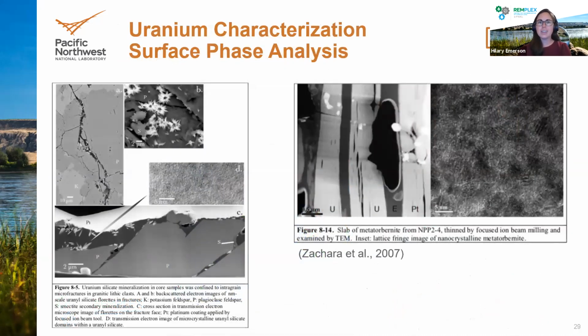And so the last technique that I wanted to highlight is transmission electron microscopy. And this is kind of the smallest scale that we can go to. And with this technique, I have two examples. On the left are some images where they identified a uranium silicate mineral. You can tell by the morphology, these white spiny structures, and also based on measurement of the lattice parameters, which was done based on the image in part D. So you can actually see the coordination of the layers of the mineral as it formed. And on the right is a copper uranyl phosphate phase that was identified by transmission electron microscopy.